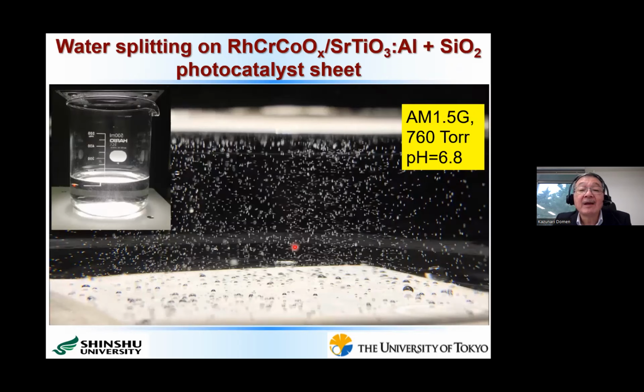But anyway, we use this co-catalyst-loaded strontium titanate and nanosilica particles mixed in aqueous solution and then spray coated on a frosted glass surface, then dried at 90 degrees C in air. That's all. It's a very simple preparation procedure.